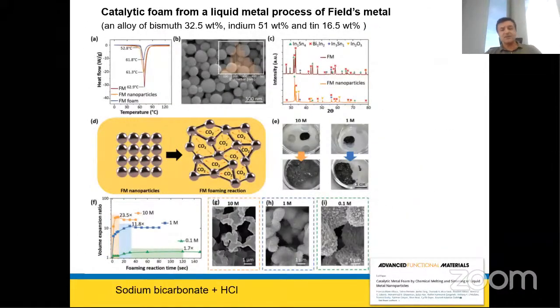Now, you can do other cute things with liquid metals. For instance, another example, we made a metallic foam, the metal oxide, functional metal oxide on the surface. How did we do that? Here, the example is another liquid metal. It's called Field's metal. Field's metal melting point is 61 degrees. It contains 50% indium, 32% bismuth, 16% tin. You mix them together, it's eutectic.